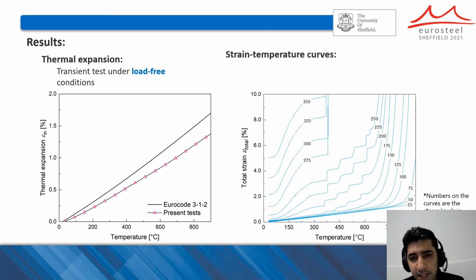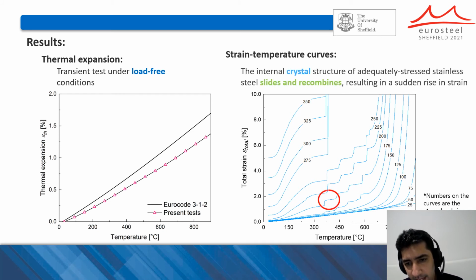And in the next figure, you can see strain temperature curves obtained at 14 different stress levels. The numbers shown on this diagram are the stress levels in megapascal. As you can see here, we have some sudden jumps occurring in the strain temperature curves at stress levels greater than 150 megapascal.